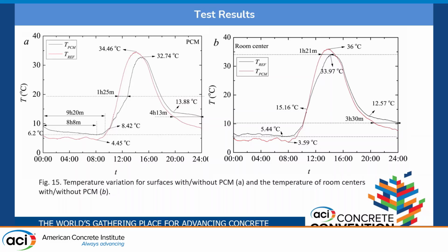We can see that during the nighttime, for 9 hours and 20 minutes, the PCM specimen has a higher temperature than the reference specimen. One of them is around 8.42 degrees Celsius, the other one is around 4.45 degrees Celsius.